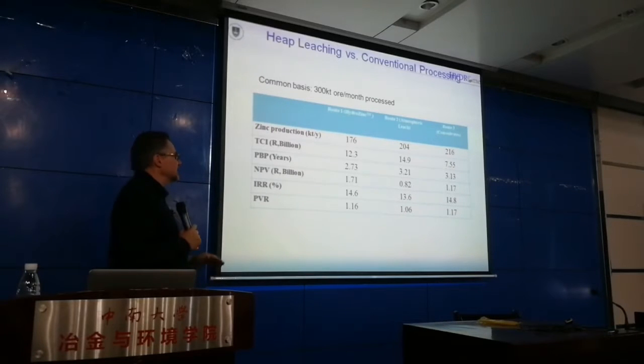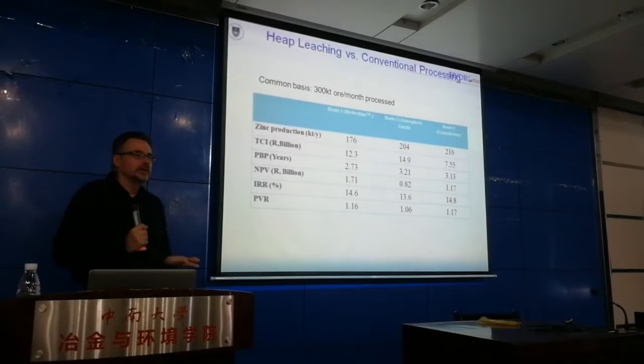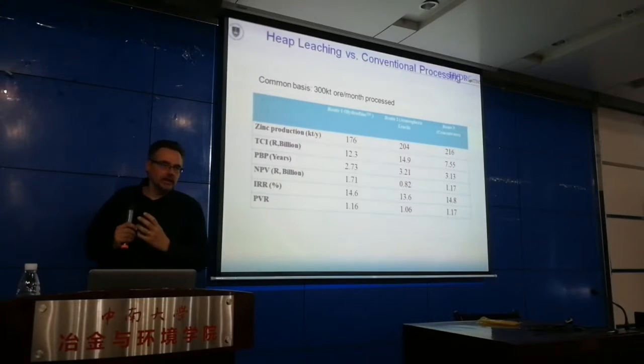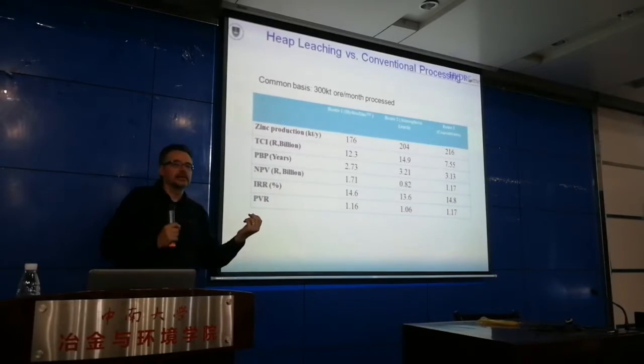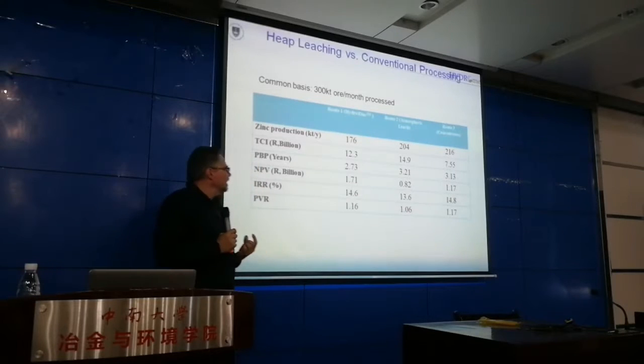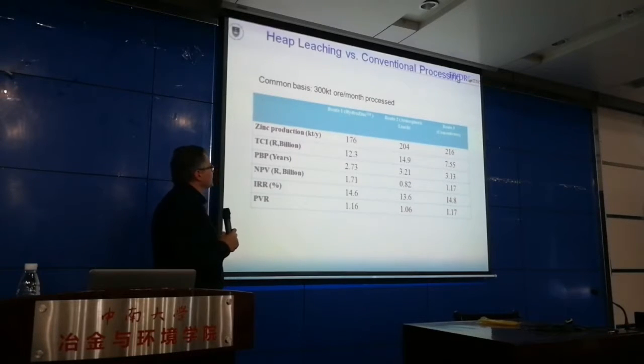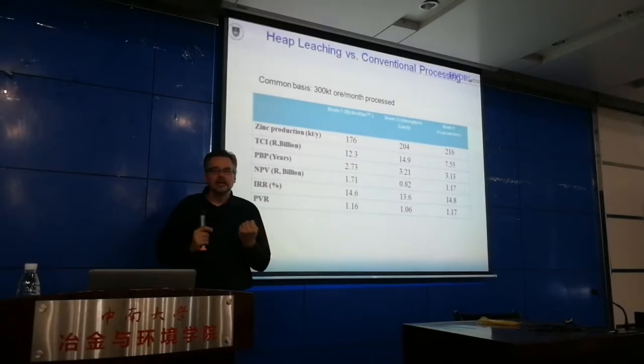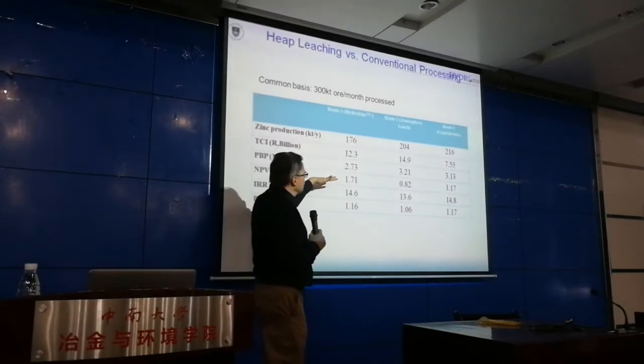So we did a study, this is the slide that's missing here, and I apologize for that, where we asked: what if it takes longer to extract from the heap? Then you end up with a higher inventory cost, because you mine your rock today, put it on a heap, and let it sit there for a few months before you get the zinc that you can then sell and get your revenue from. That's referred to as the inventory cost, and it is very strongly dependent on how long your material sits inside the process. With heap leaching, we found that if the process is not operated optimally, then the inventory cost goes up dramatically, and the net present value